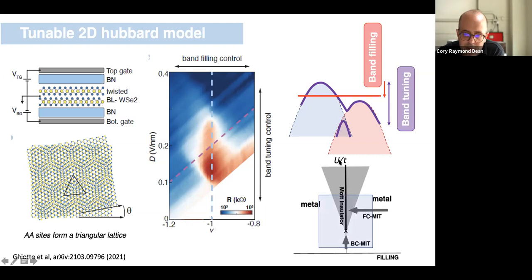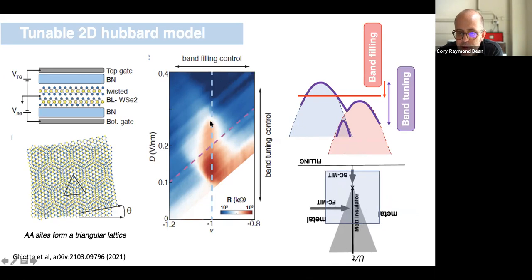Okay, so just to orient yourself here, here's the generic cartoon diagram. What we're able to do is tune completely through this space, or maybe a simple way to understand this is if you just flip this over, right at this point is the point that maybe corresponds to this point in this diagram. So as I increase the displacement field, I increase the bandwidth in this system. So I tune from a strongly correlated system maybe to a weakly correlated system. Okay. The other thing to keep in mind is that this window, we can access fully through, again, symmetric and anti-symmetric bias gate voltages.